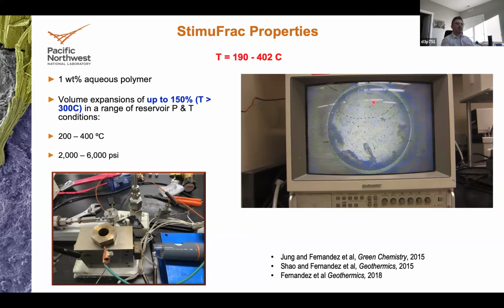Usually you have supercritical CO2 on one phase. You may have some dissolution of the CO2 into the water, but the dissolution here is fairly large, to the point that you see a single phase in the cell associated to the volume expansion triggered by the reaction of CO2 with the polymer and the dissolution process and of CO2 expanding that fluid.